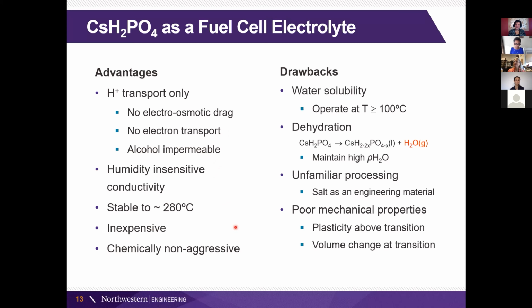The electrolyte is also chemically non-aggressive with respect to the catalyst, platinum in particular. So again, if you compare that to the polymer systems, the polymer tends to dissolve and reprecipitate the platinum, so it coarsens. But there are some drawbacks, as I said. The material is water soluble, so we have to operate at above 100 C. There's also a challenge of dehydration. So we have to maintain a sufficiently high water partial pressure that we don't have this reaction occurring.